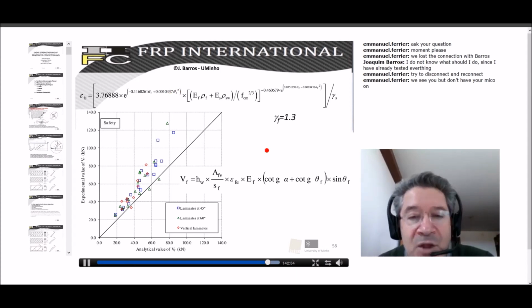And using a safety factor of 1.3, we proposed an equation that in fact estimates with good accuracy the values registered experimentally. So this is a relationship between the analytical values predicted by this equation and the experimental ones. We realize that almost all the values obtained experimentally are on the safe side.